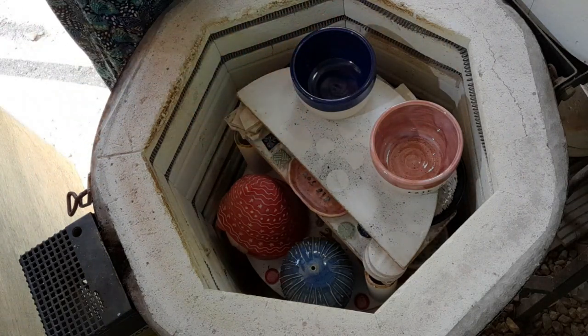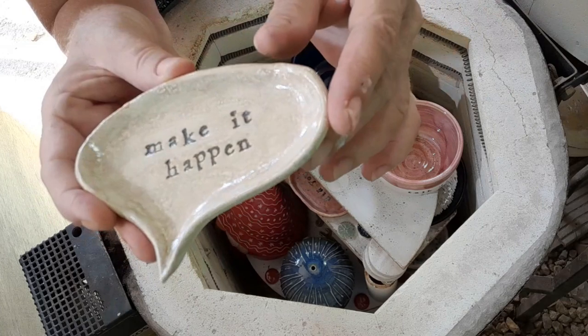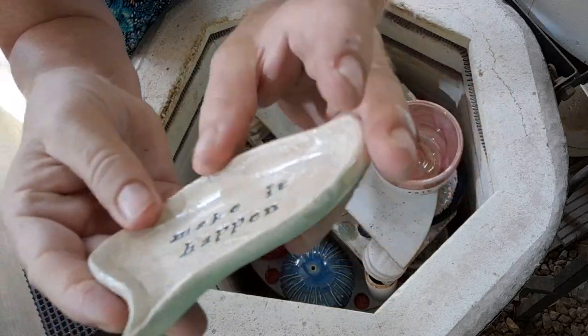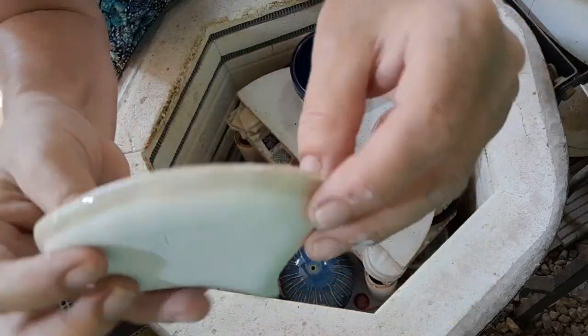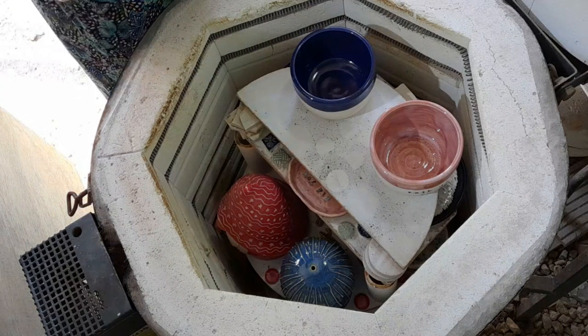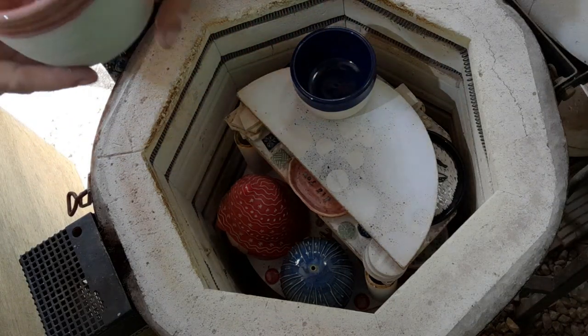This is another little text balloon dish. This is the regular oatmeal by Amaco, and it always does that for me — it always crawls. It's not the dust; it's the only one of my glazes that does that. I think I need to put it on thinner. It always becomes like yogurt in the jar, and I try to thin it out with water but that doesn't seem to work, so I need to figure out something.